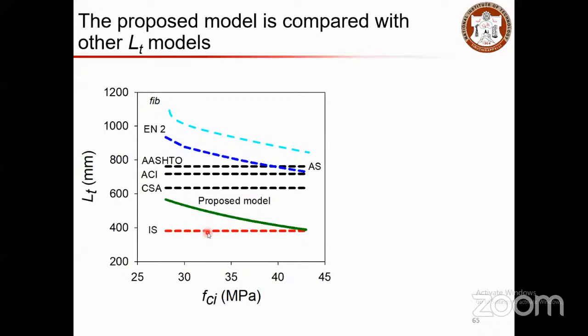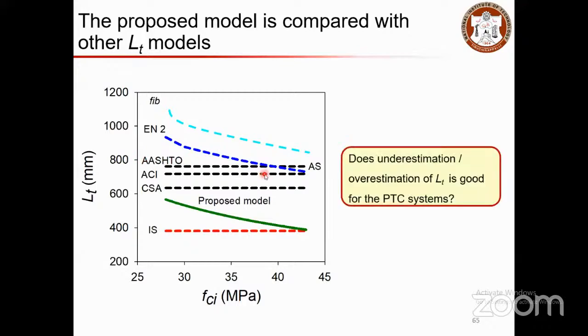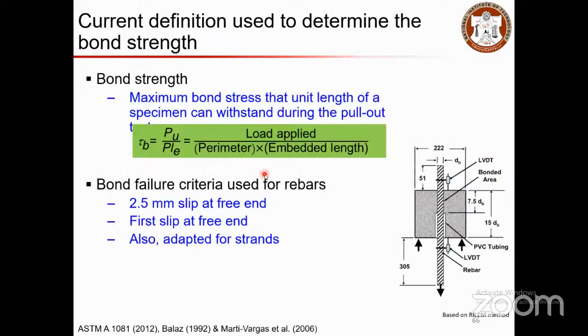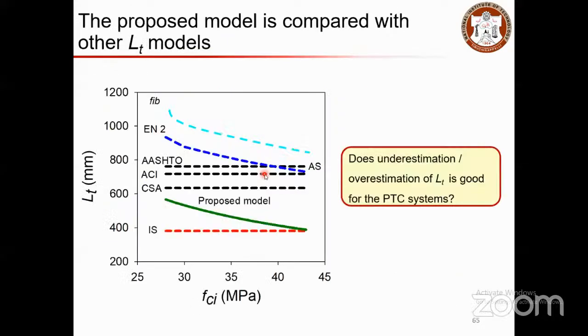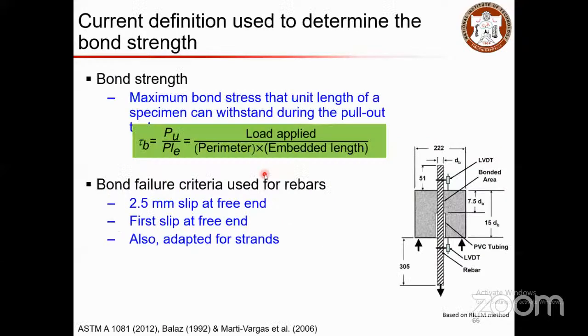Similarly, based on the model, this was compared with the other standards as well. From the comparison, it is understood that our Indian code underestimates the values significantly, and there are codes that overestimate the values, but that is not constant and not reliable all the time to go with. So yes, underestimation and overestimation of the transmission length is not always good for a pre-tension concrete system. So let us understand how the bond mechanism is being affected.